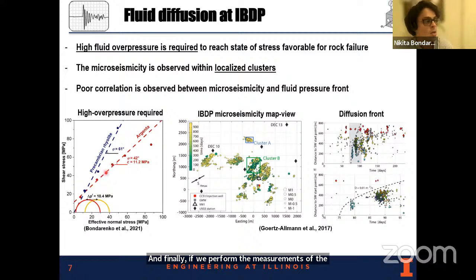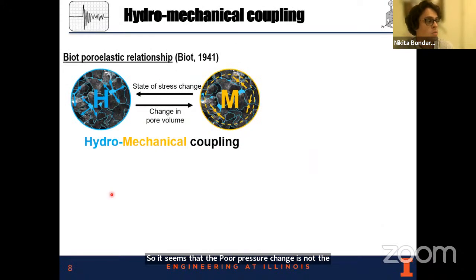And finally, if we perform measurements of the strength of rocks extracted from this formation, we can see that the injection overpressure needed to reach failure condition is very high, on the order of 10 MPa, and the maximum overpressure recorded during the project was only 1 MPa.